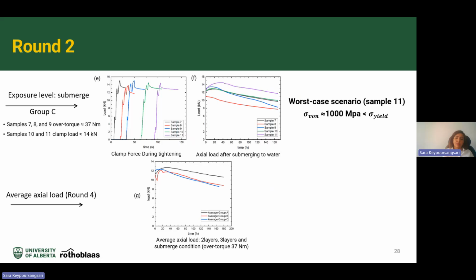But after a while, this moisture penetrates inside the wood. So we know that below the fiber saturation point, material properties of wood change significantly with the moisture, so it affects the stiffness of the whole structure. And also based on the literature review, moisture content has negatively affected the withdrawal properties of connections. So the strength and stiffness of the connection decrease as well. That's why we see this load starts decreasing only a few days after moisture penetrates inside the wood.